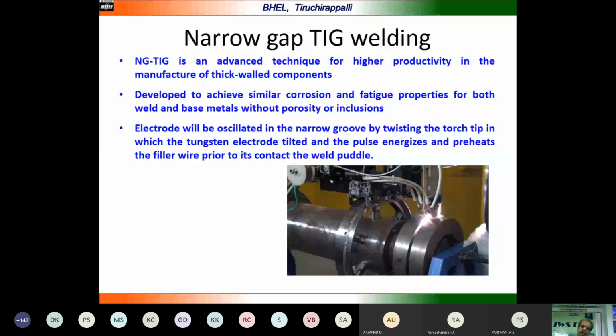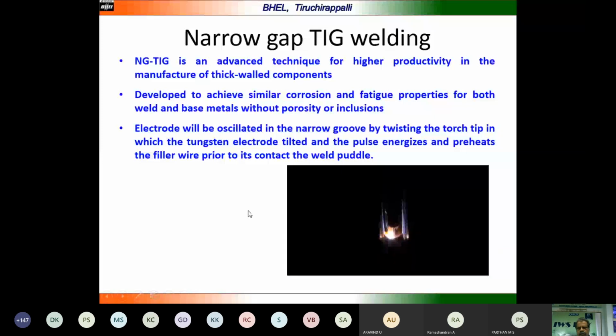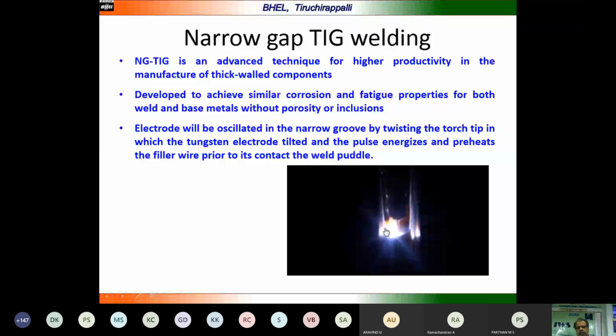What is happening in the process? What you see here is the narrow gap TIG welding process, and you can see the torch is getting oscillated, and because of the oscillation, it ensures the penetration on the side wall. So there will be no lack of fusion on the side walls. That is the advantage of this technology what is available now.